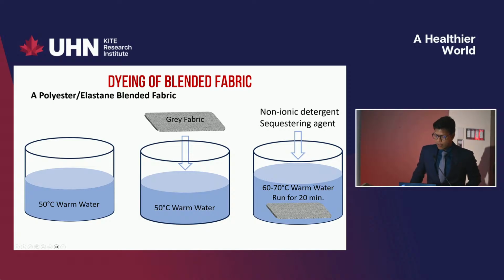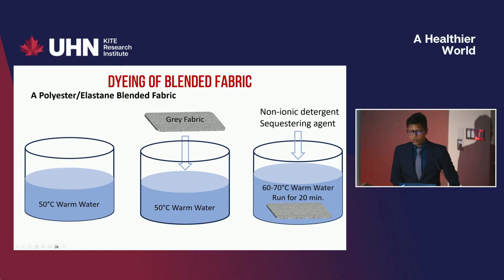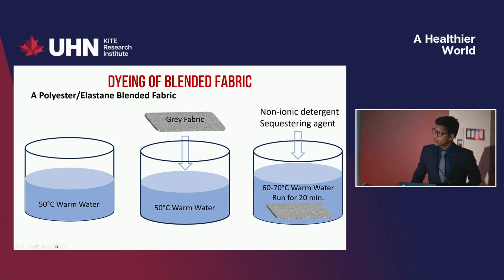And we also use a non-ionic detergent to get the oil out from the fabric, which came from previous processing of the fabric. Here in this case, we increase the temperature to 60 to 70 degrees centigrade. This temperature is close to the glass transition temperature of the polyester fabric, and it emulsifies the oil. So we run the fabric, for instance, for 20 minutes, so that we can get rid of all the oil and impurities in the gray fabric.